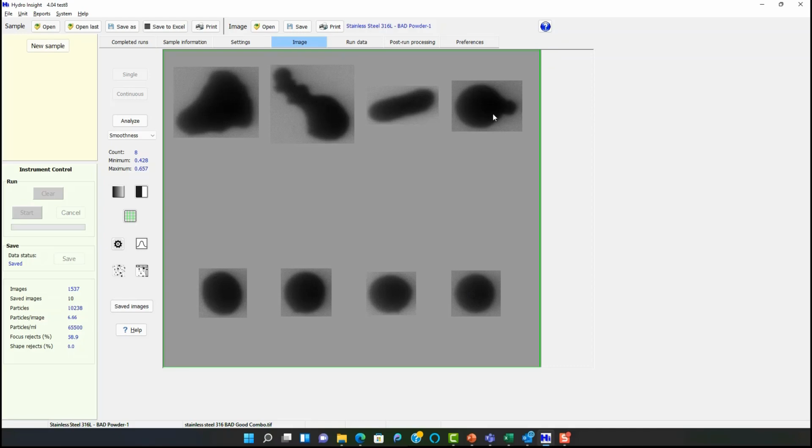These are particles that can be partially fused to other particles during the deposition process. They can be elongated, or they can be many particles stuck together, again, due to the deposition process and the melting and sintering process. Trying to glue these particles, sometimes they get glued together. So again, looking at just particle size is a way to differentiate the particles.